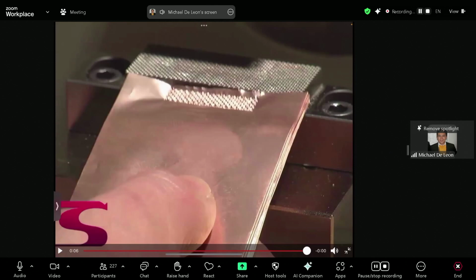This application is particularly for the superconductor or REBCO superconductor applications. But of course, challenges still remain, like the electro-thermomechanical performance of the joint, which is very important. Also, there is limited data under dynamic loads, particularly low cycle fatigue and high cycle fatigue conditions. And joint robustness for high volume EV production is still a concern, along with thermal management under certain environments, like cryogenic temperature.